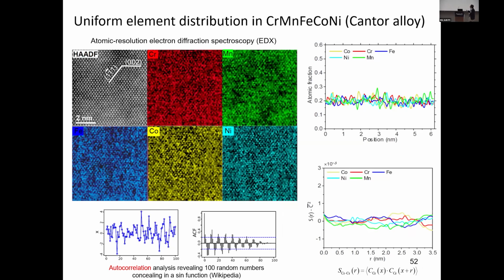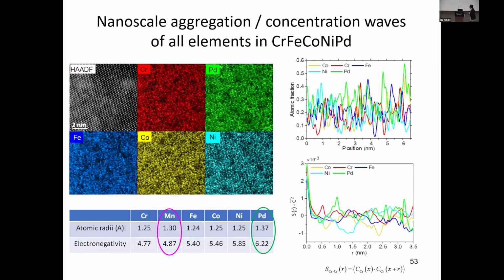We first use atomic resolution mapping to resolve the element distribution at the nanoscale. For this reference Cantor alloy, we got almost a uniform distribution of all 5 elements at the nanoscale. So we use this atomic resolution EDX map for the new high-entropy alloy. You see very strong compositional fluctuation at the nanoscale. It's kind of understandable because Pd has a very different atomic size and electronegativity compared to other elements, or compared to the Mn. So that can cause a very strong nanoscale compositional fluctuation, not only of itself but also of other elements, as shown by those autocorrelation analyses.